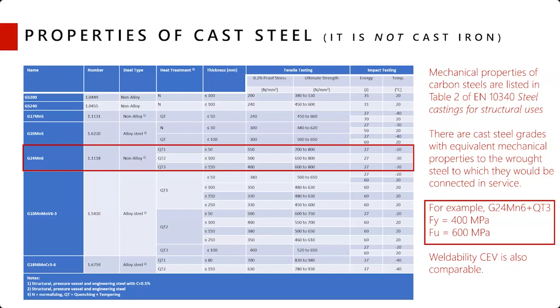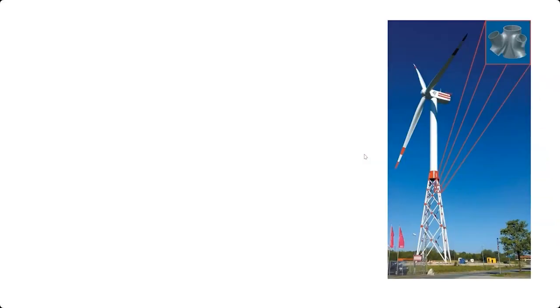Yield stress of 400 MPa, so that's putting it close to your S355. So the mechanicals, the weldability, the carbon equivalent, all of that that you're going to see is going to be similar for these cast steel grades, which again are all standardized in Eurocodes, as well as when we work in other locations, it would be through ASTM specification.